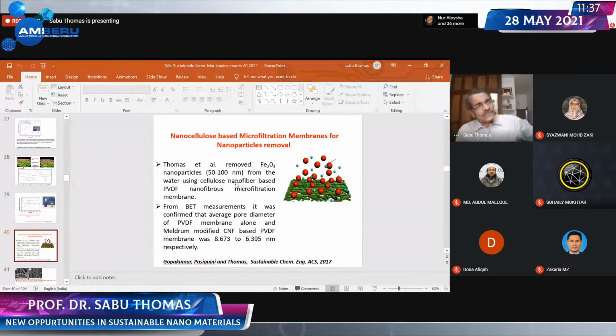Probably you all know that water is increasingly contaminated with suspended particles, metal oxides. So we focused on iron oxide in the range of 50 to 100 nanometer. What we did is we gave a coating with the nanocellulose dispersion on the surface of the filter. And when you do that, the pore size becomes around 8.6 to 6.3 nanometer. So all the suspended particles in the range of 50 to 100 nanometer could be retained at the top surface of the filter because they are big.